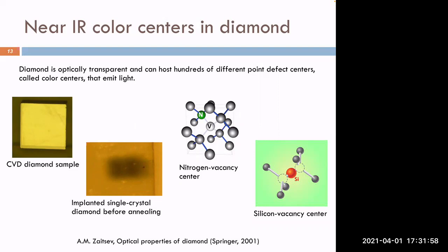And to get rid of this problem, then what we do is to bring the diamond into a very high temperature furnace. We are talking about 1200 degrees for an hour, 2 hours or so. And then this will essentially do two things. Heal the lattice defects, so the diamond reacquires the transparency, and at the same time, it will give enough mobility to silicon ions and vacancies to find the configuration that you see here of the silicon vacancy center. So after this annealing process, basically, then you have your quantum emitter.